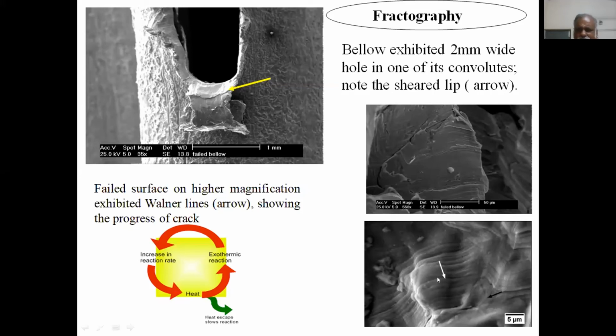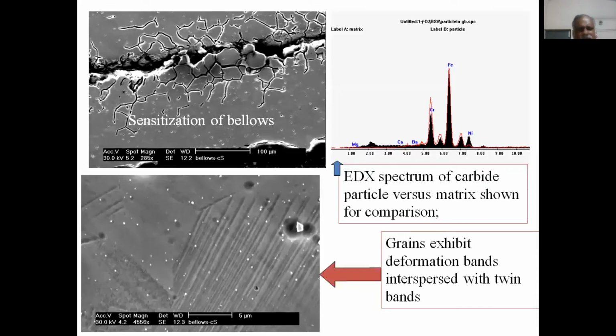In detail, if you look at it, you find the development of twin bands along with a lot of striations, which suggests that there is also a fatigue effect caused by the interactions. Okay, what could be the reason why this has developed? It was a leakage wire. So we tried to see between the two plies through spectrography. The two plies carrying the sodium debris here exhibit an interesting microstructure. People working in stainless steel will know that this is sensitization.